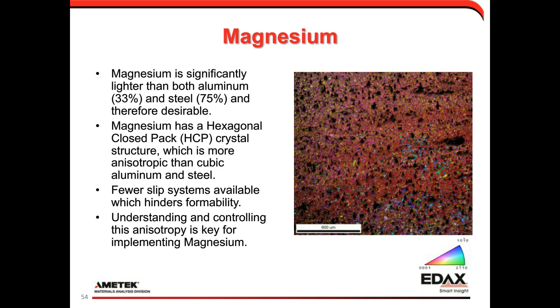So the third material alloy I want to talk about is magnesium. Magnesium is attractive because it's lighter than aluminum and steel, so it's desirable. It has the mechanical properties you want. But magnesium is hexagonal close packed. It's a hexagonal crystal structure, which is inherently more anisotropic than aluminum or steel, which are both cubic. And with that, magnesium will have fewer slip systems available, which affects the formability. And so being able to understand and control the anisotropy is really a key factor for being able to implement and integrate magnesium into an automotive application.